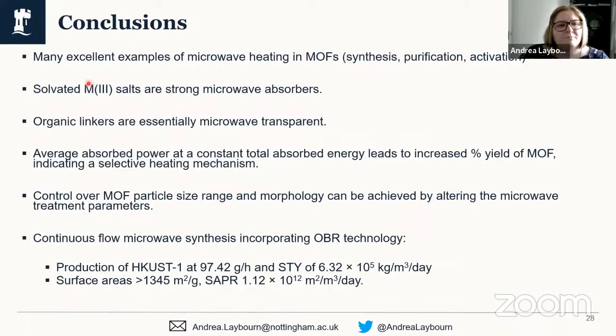I've shown you from work that we've carried out at Nottingham that solvated metal salts are strong microwave absorbers and that organic linkers are essentially microwave transparent. And so this is information garnered from the dielectric properties measurements. And this fits in with the mechanisms that we'd expect to see for heating with microwave fields.